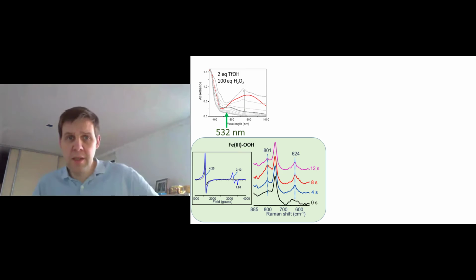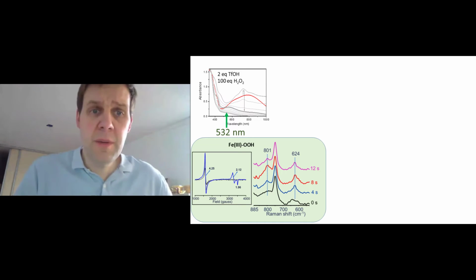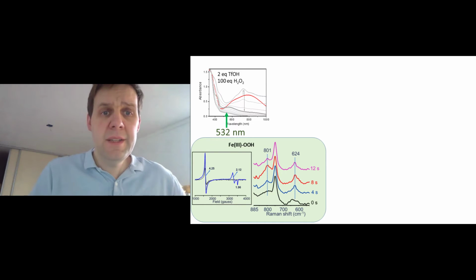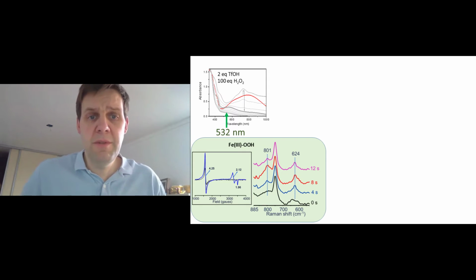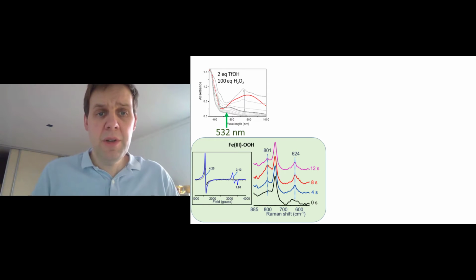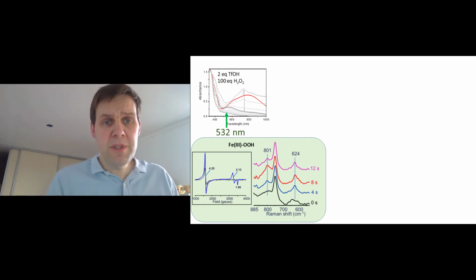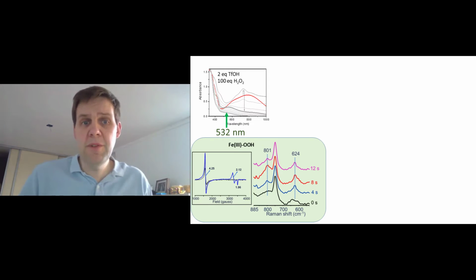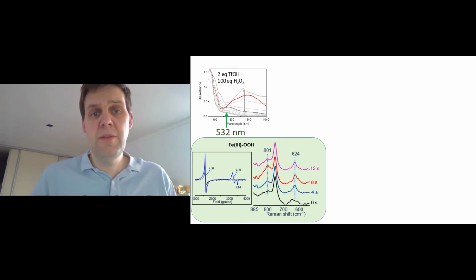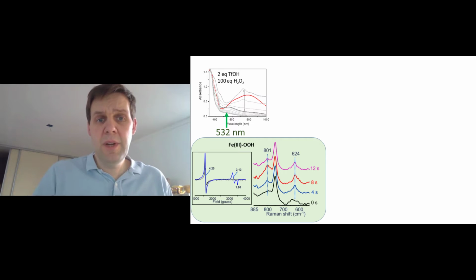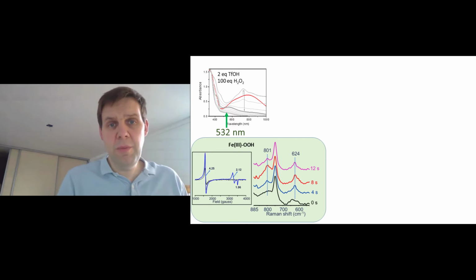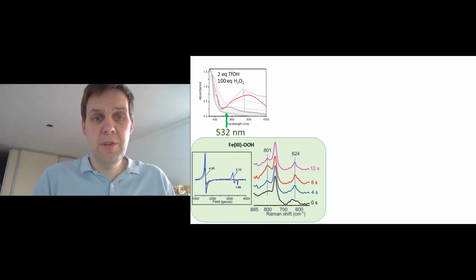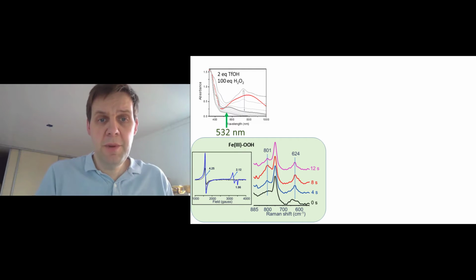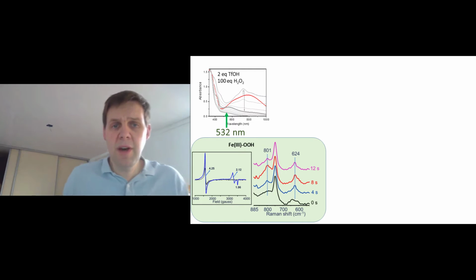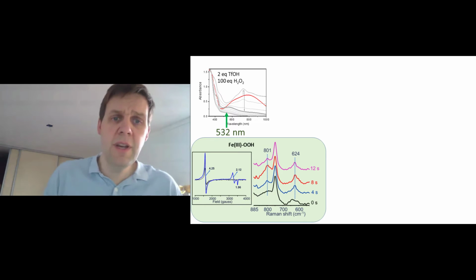So we take a laser at 532 nanometers to run a Raman spectrum, hitting into this absorption around 600 nanometers, or around 560 nanometers. And we record an EPR spectrum of the sample, which is flash frozen. So we freeze the sample within 20 seconds. So you add the peroxide, mix, and then quickly freeze. You quench, you stop time essentially in the frozen solution. You can run an EPR spectrum. The EPR spectrum tells you this time we have a low spin iron 3 hydroperoxy.